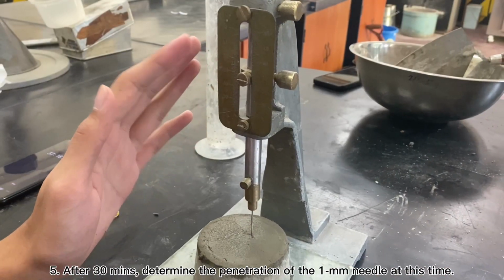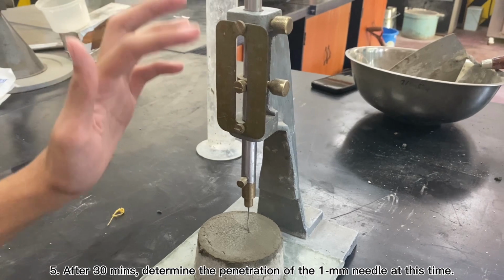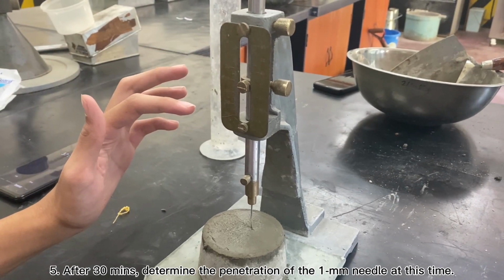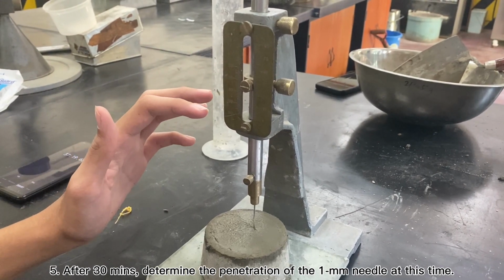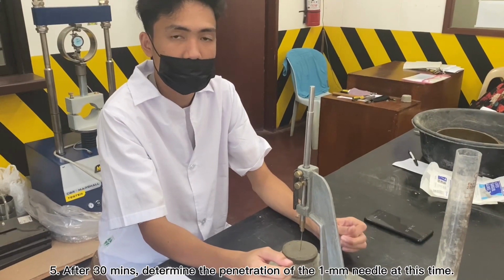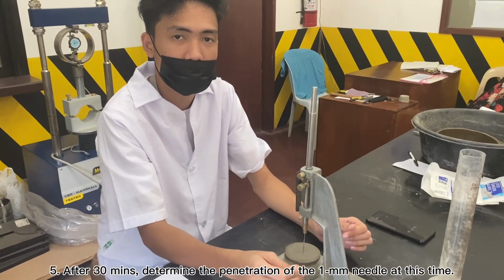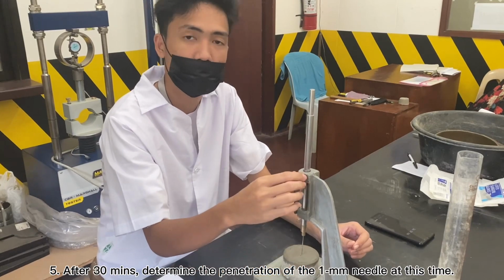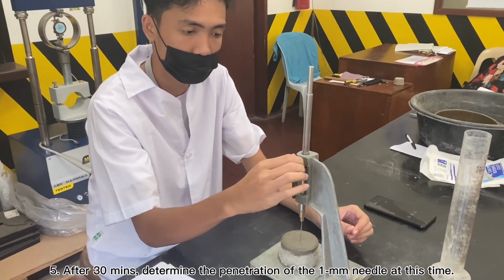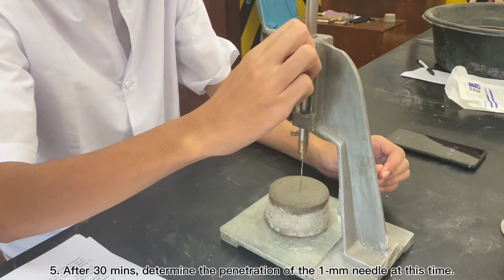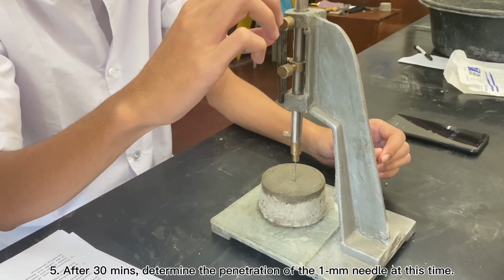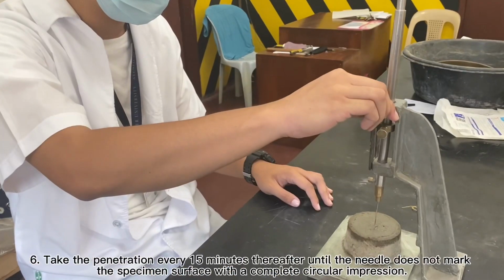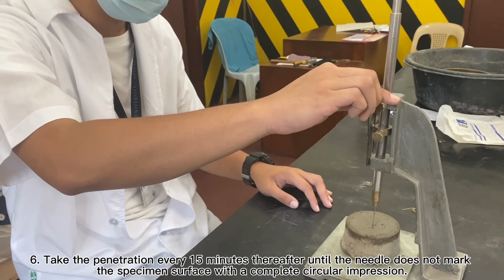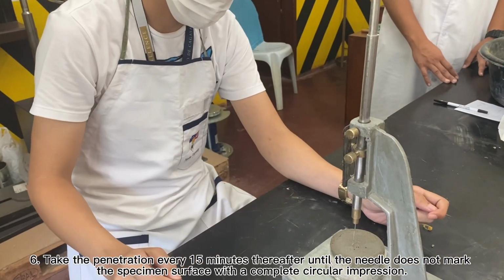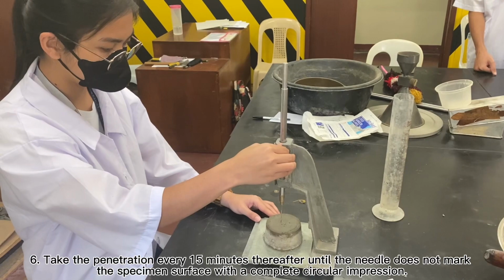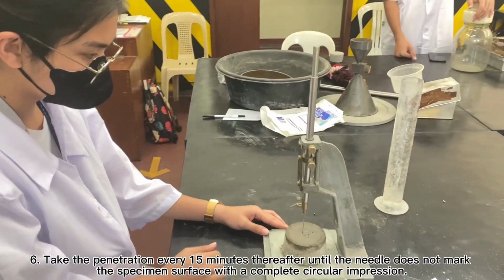After 30 minutes, take the first penetration. Make sure that the needle is just above the specimen. So after 30 minutes of settling, we will perform the first penetration. Make sure to record your data. Take the penetration every 15 minutes thereafter until the needle does not mark the specimen surface with a complete circular impression.